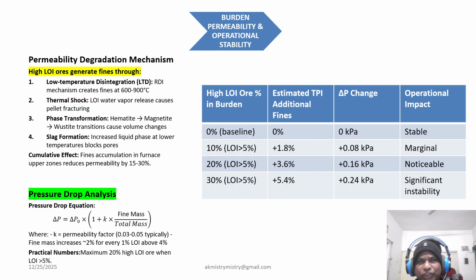Now the maths works like this. The pressure drop, that is delta P, is already calculated and given as per the formula in the slide, where K is 0.03 to 0.05, and for every 1% LOI above 4%, fines increase by 2%. So if you use 30% high LOI ore, expect a 0.24 kPa rise in pressure, which is enough to destabilize the blast furnace burden movement, and further there is a huge process upset.